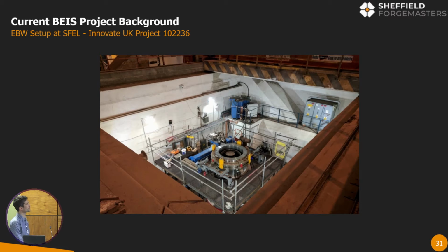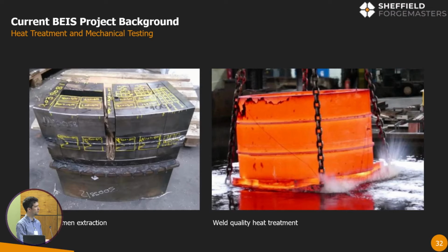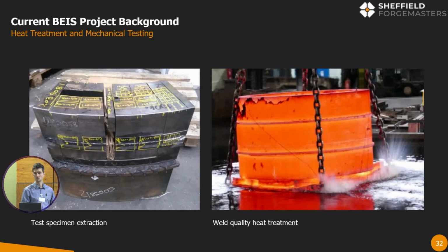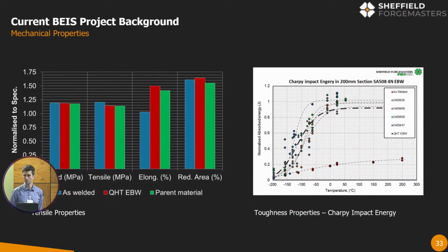So we took that test piece, which is shown glowing orange on the right there, and subjected it to what we call a quality heat treatment, which is the heat treatment where we essentially set the microstructure and mechanical properties of that component for when it enters into service. Once we heat treated that, we then took a load of mechanical test pieces out of it. The reason we did that was it was predicted that we'd be able to achieve or exceed parent material properties within that weld.